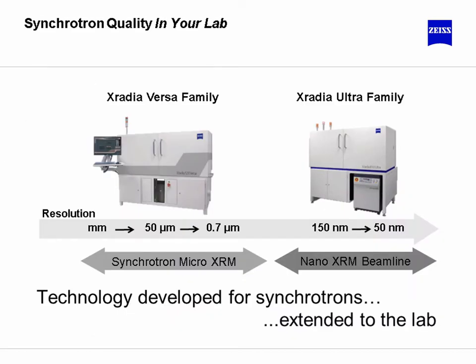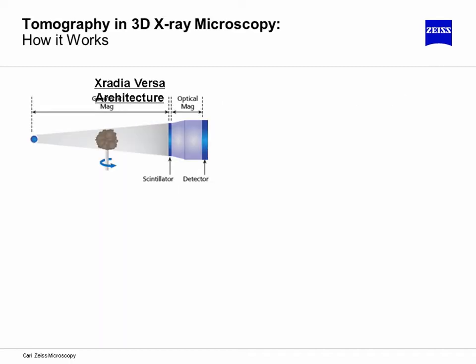Now, resolution-wise, you saw in the previous graph, submicron microscopy runs the gamut from spatial resolutions approaching half a micron, so officially 0.7 microns, up to tens of micron voxel dimensions, whereas the nanoscale area requires generally smaller fields of view, smaller specimens, but is now able to obtain tens of nanometer spatial resolution with a minimum voxel dimension of 16 nanometers.